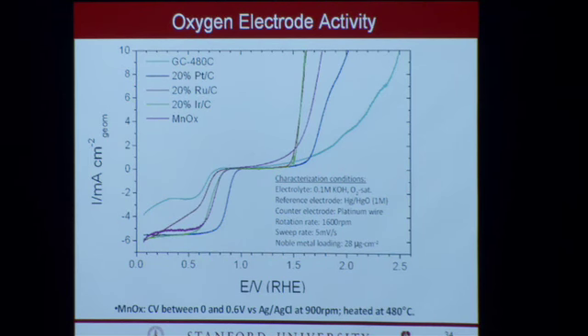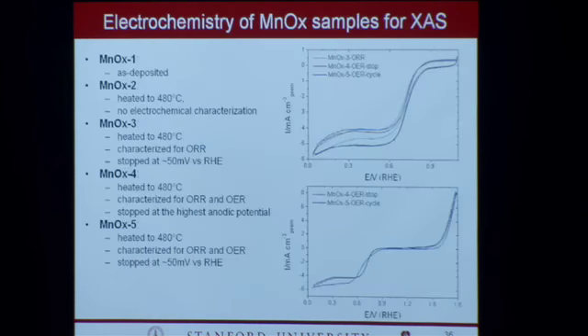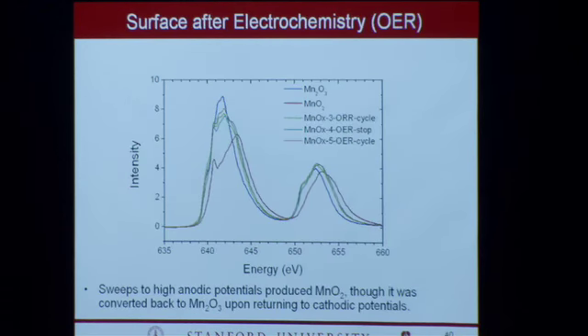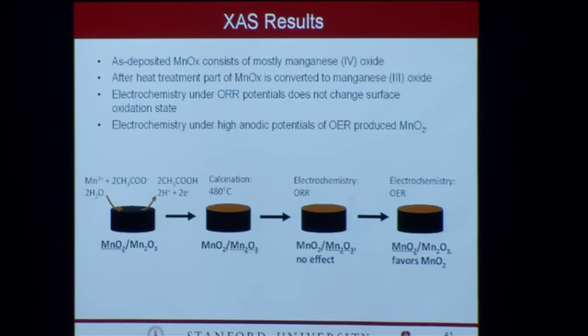So this manganese oxide, by changing the synthetic parameters, by changing the structure of that manganese oxide surface, by changing our processing conditions to heat it to form the right phase, we've been able to make extremely active catalysts for both oxygen reduction and oxygen evolution on a non-precious metal material. So I'm going to skip a few slides here where we went up to the synchrotron at SLAC to understand what the phase was of our manganese oxide during operation. And this is the slide that really sums up that work. When we synthesize our manganese oxide, it is mostly MnO2 with a bit of Mn2O3.